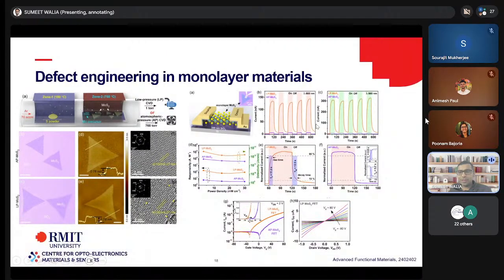We have been looking at transition metal chalcogenides, WS2, MoS2. So here is an example of MoS2. So what we demonstrated in this study is, as you can see at the top, just under the tube, we grew MoS2 crystals, monolayer crystals, using slightly different parameters. So essentially what we did is control the amount of oxygen that is present during the synthesis. When you have a lower pressure during the synthesis process, energetically MoS2 tends to harbor sulfur vacancies. And when you have more oxygen in the system, this oxygen actually passivates those sulfur vacancies. And that's what we are calling atmospheric pressure, because there's more oxygen in the system.